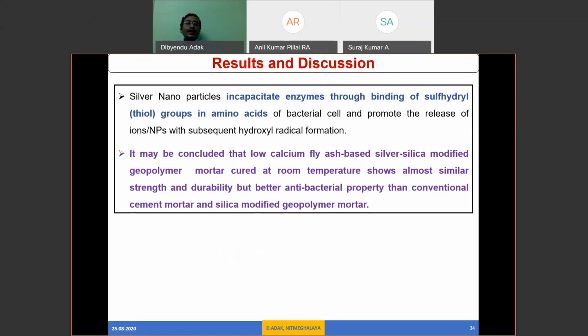And finally, what we can conclude is that we have prepared the silver silica nanomaterial-based composite. The main reason is that the silver nanoparticles destroy the amino acids present in the bacteria, and the silver nanoparticles release and produce hydroxyl radical formation. Hydroxyl radical formation means they will destroy. They will take part in the reactive oxygen species. So in the presence of silver nanoparticles, they easily destroy the bacteria.